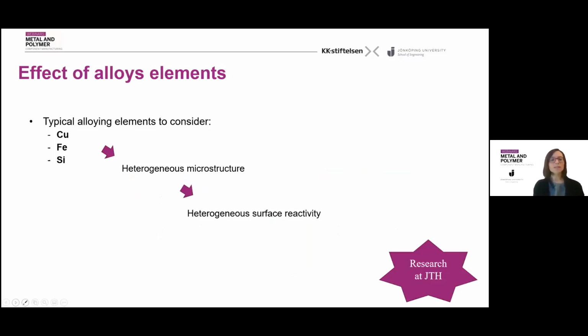When it comes to aluminum, we work mainly with alloys. Typical alloying elements we should be really careful with are copper, iron, and silicon. These three elements are really common in aluminum alloys, and they can be in solution in the structure, or they can form second phases and intermetallics of different types. Therefore, they produce a heterogeneous microstructure, which ends up creating heterogeneity in surface activity and capability of forming bonding with the next layer. This is actually something we do a lot of research on here at Jönköping University.